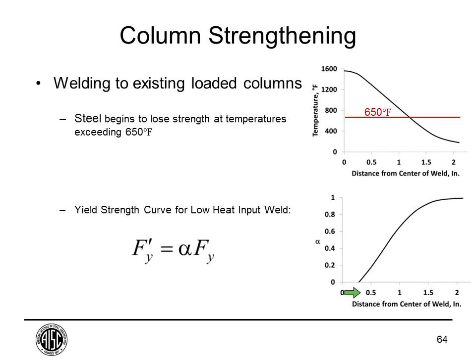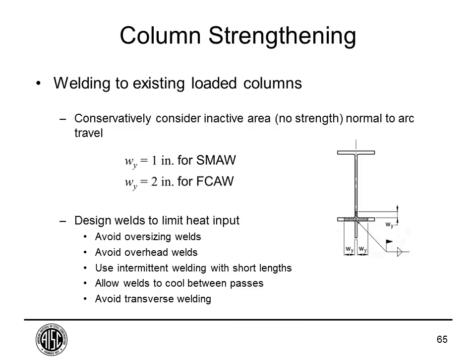And then this is a relationship of the distance from that weld to the strength. So you can see that at about 1 inch away, you have about 60% of the steel strength, and then as you get closer to areas within a 1/2 inch of the weld, you have almost no strength. So how this is typically dealt with in design if you're welding to a loaded column is you consider the area within an inch or two of the weld to be ineffective, basically no strength in that area, and then evaluate the remaining section and make sure that that is still adequate for the loads, not the final loads, but the loads that are present at the time of welding. And again, you'll want to follow these general guidelines in order to try and limit the heat input to the existing steel.